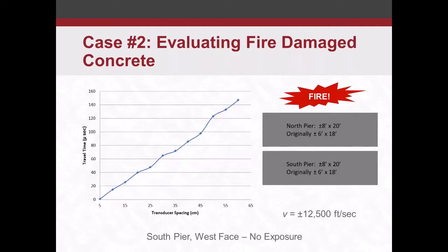And when we plot that, we get something like this. This particular plot was on the south pier west face. This is the one that had no exposure. Our calculated wave speed was about 12,500 feet per second, which is pretty typical, 13,000 for maybe 4,000 psi concrete. If you recall our other project, we were getting up to 16,000 feet per second. That was 5,000 psi and above.